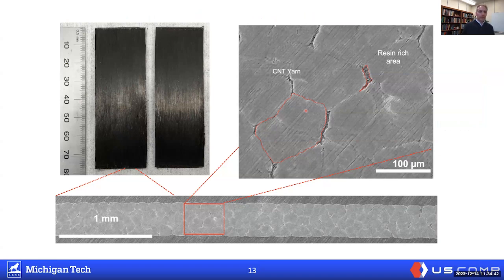All right, so the FSU team, Cecil and his colleagues, what they did, they made some composite panels out of these. So you can see on the upper left here, these are the panels. If you take a look here at a cross section of these panels, this is one of these panels. It's embedded in epoxy. So what you're seeing at the top and bottom here, that's just the epoxy it's embedded in. That's not part of the composite panel itself. If you take a look on here, and then you see this magnification of what's going on, you see these little individual regions outlined in red. Those are carbon nanotube yarns.